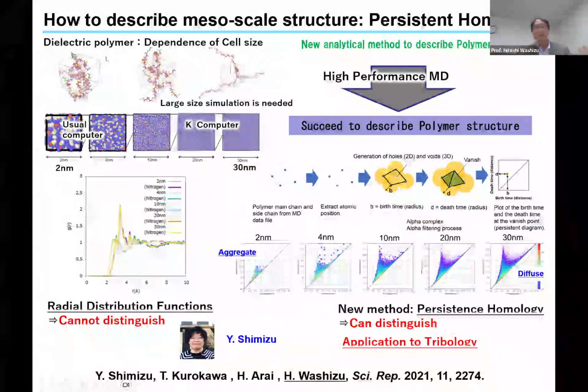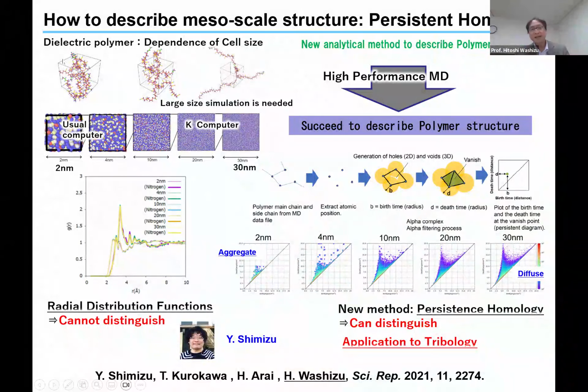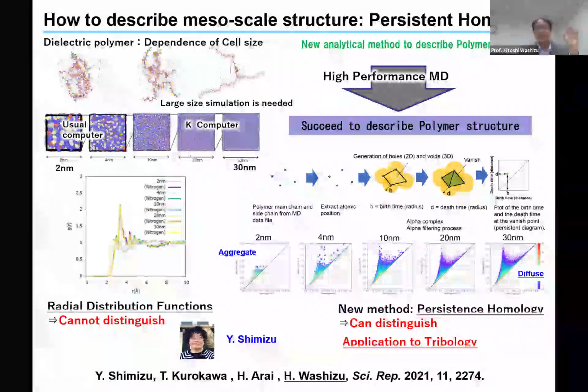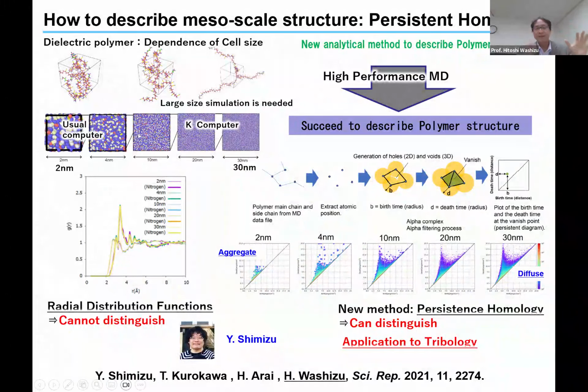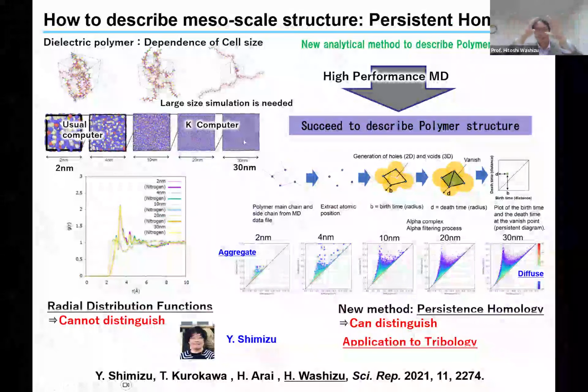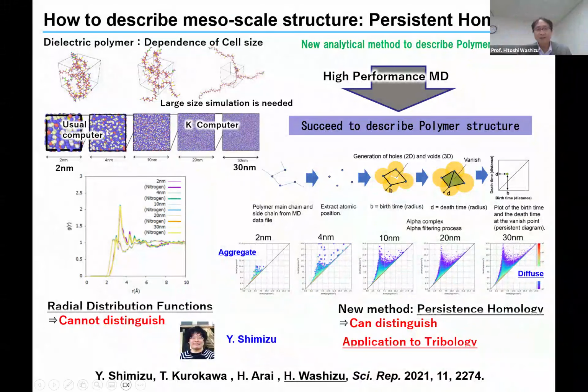We use these kinds of polymer for the actuators, and we'd like to know the dielectric constant. But we need a large simulation cell size, so this is a computer simulation where we change the cell size. With a usual computer, we cannot make such a large simulation cell, but using the supercomputer named K, we can prepare a very large system, and then we calculated the dielectric constant.